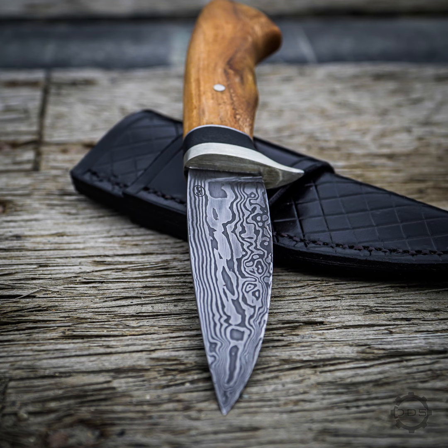So finding out basically if the blade was heat treated, tip to tang, would be a good question to ask. And then your steel type. So just keeping in mind that if you go with a really high alloy steel, like ATS 34 or D2, the list goes on, 440C, these are stainless and really high alloy steels, and they typically have a tip to tang heat treat, an oven heat treat. It's not bad, but it's going to be geared towards a specific purpose. Now, people will build them very robust, so they're very hard to break. I want to add that in too. I'm not saying they're just going to snap.